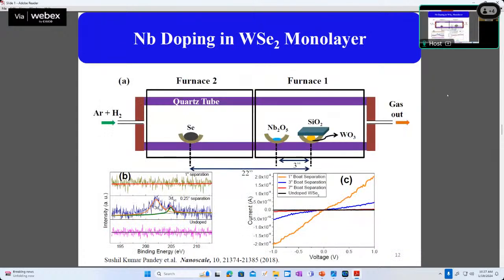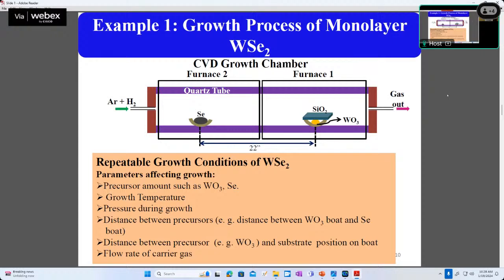Now, sometimes we actually need good conductivity of a material for its application. So for that purpose, we did doping of this material. For doping, it is very simple. Whatever setup you have, you keep the dopant related material in another boat near whichever precursor is suitable. For this one, niobium oxide powder was a suitable material to dope this material with niobium, and we kept this near the WO3 boat. So whatever you have seen in the previous setup, there is only one change. Here we are keeping a different material near furnace one.